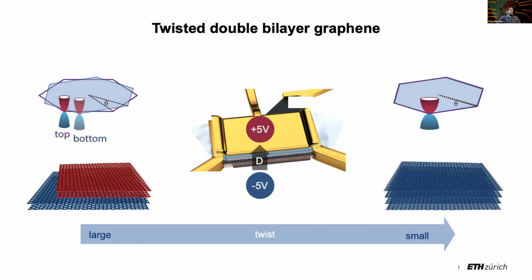Again, I show top gate versus bottom gate voltage. Now everything is recorded at a magnetic field of 1.5 Tesla, because then you see some sort of oscillations, Shubnikov-de Haas oscillations, which tell you how the Fermi surfaces look like. And I took the numerical derivative just to make these oscillations appear a bit clearer.